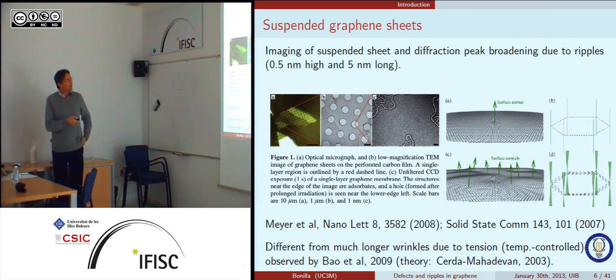Now, one thing that you see is this. The microscope is calibrated at about 80 kilovolts, which means that if you have a pristine graphene layer, you cannot knock atoms out of it because it's low energy. However, if there are defects or impurities there, these electrons may knock atoms off around the hole, because the energy for that is lower, or they can change or rotate bonds, and that creates defects. So this is part of what I'm going to talk about.